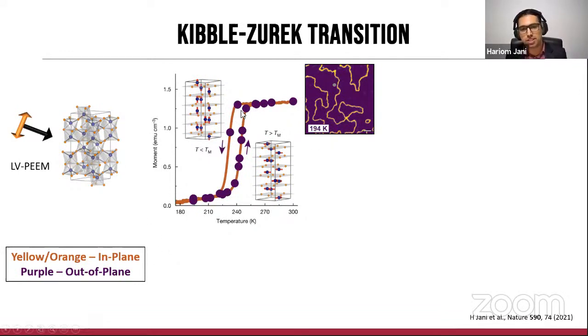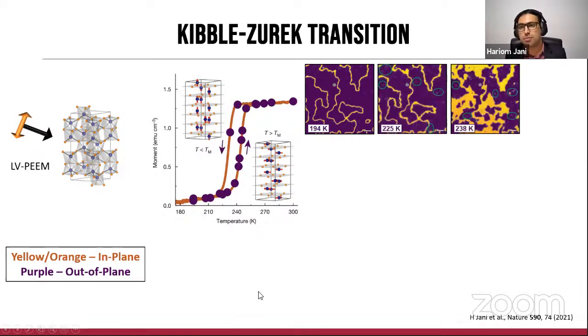As we now warm the system towards and across the Morin transition, we observe very interesting phenomenology that these domain walls start to firstly widen. And at the same time, there is emergence of lighter regions in the matrix that starts to happen. These lighter regions correspond to the emergence of in-plane domains which are nucleated, which is matching very well with the understanding that the Morin transition is a first-order phase transition.